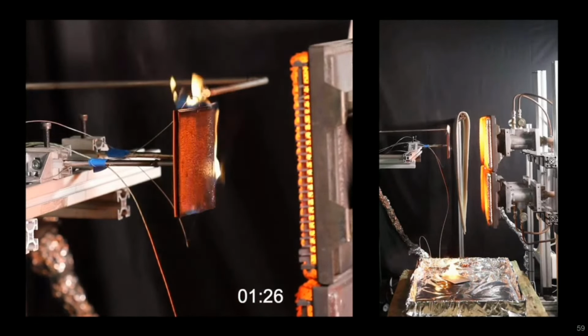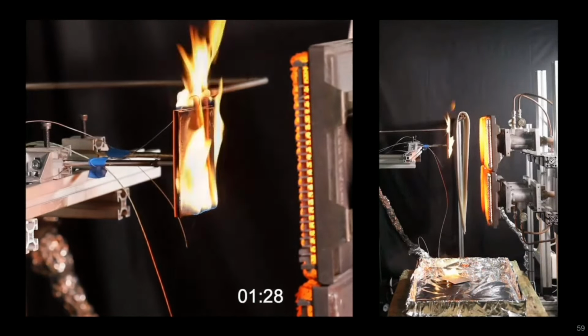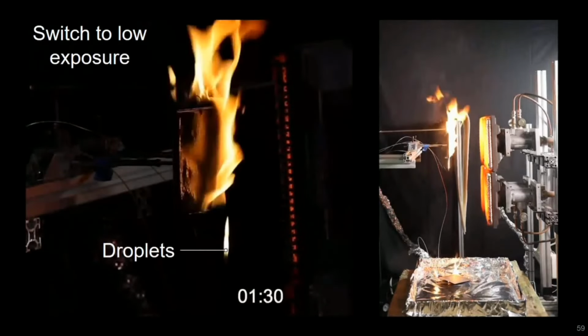Flaming then continues on the front aluminium facer, now in the debris tray, and discontinuous flames become visible over the front surface of the specimen. And you can see here we've switched to a low exposure view on the left-hand side so that we can see things as the flames grow. By 1 minute and 30 seconds, flaming is well established over the front surface of the exposed polyethylene, and the first burning droplets of polyethylene begin to fall from the base of the specimen and into the debris tray.